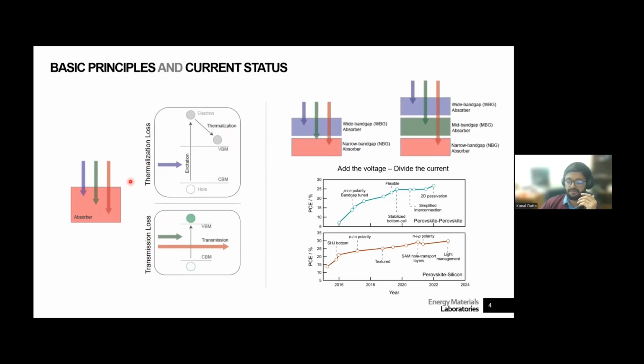These 2 are the loss mechanisms that limit single junction devices in pretty much every platform you can think of. To reduce the transmission loss, you can minimize the optical band gap as much as you want, but then thermalization will kick in, and vice versa. The way to overcome that is to make a tandem or a triple junction device, where you can go further with the number of layers. All you're doing is splitting the incident light spectrum. You use a narrow bandgap absorber to capture the low energy light, and a wide bandgap absorber to capture the high energy light. If you do it right and balance charge as well, then you get a good working device. The same applies when you go a step further and make a triple junction device, splitting the spectrum into more sets.